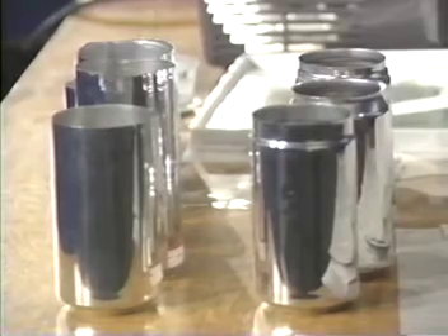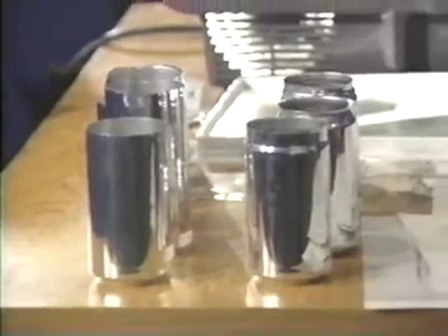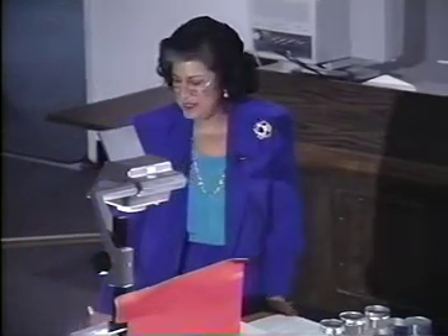And you can have billets very, very large. One facility of Alcoa's, for instance, in Alcoa, Tennessee, which is right out of Knoxville, Tennessee, produces these billets at about 30 feet long and about 10 feet wide and about a foot deep. And they come out of these huge vats of molten aluminum, pulled through a cooling chamber until a hard shell forms, and they're pulled on off and rolled on to the next cycle.